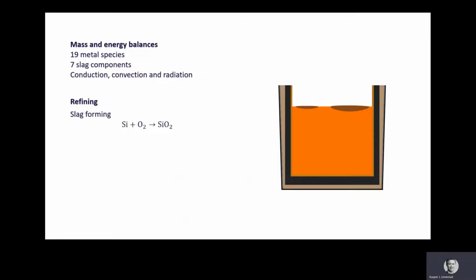Refining is a two-step process. The first step is forming the slag by adding an oxygen source, which will react with the silicon and form silicon oxide. This silicon oxide then reacts with aluminium and calcium to form their respective oxides, thereby removing aluminium and calcium from the metal phase and transferring them to the slag phase.